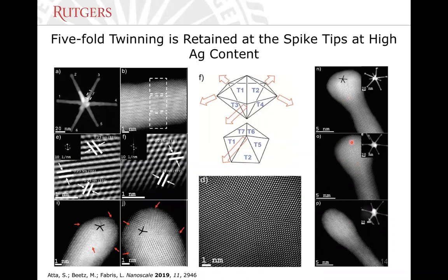So the interesting thing that we gather from this study is that silver is necessary not only to impart the anisotropy to start growing the spikes, but also to keep them from reshaping, to keep them from shrinking over time. And this is very important for these types of nanostars, because the small radii of curvature mean that these positions on the nanoparticles are very highly energetic. And so we don't want them to give in to thermodynamics and reshape very rapidly.